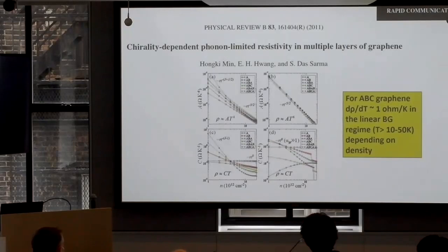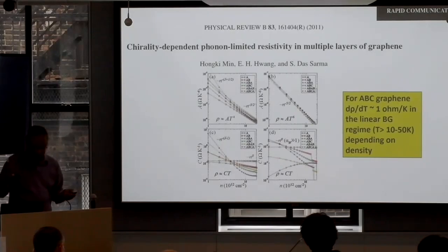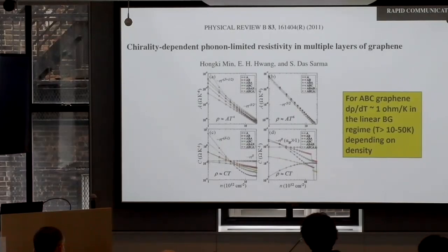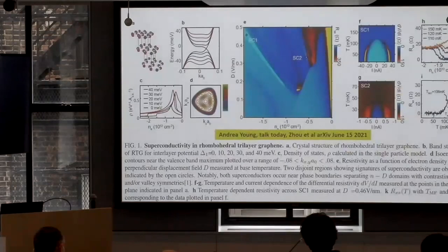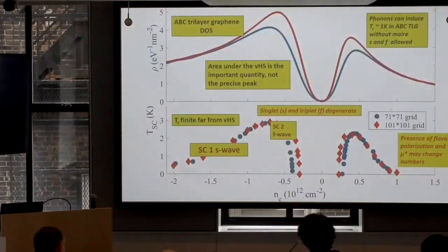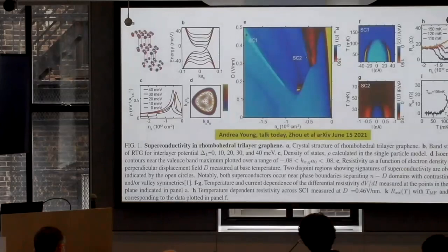A long time ago, we pointed out that for graphene, we originally did monolayer, but you can have multilayer graphene, and you can calculate now, and dρ/dT is 1 ohm per Kelvin, because again it's very small, because the electron-phonon coupling is very weak, and we calculate for all these different materials. So we can now compare, and our prediction is, and this is a very important point, everybody should pay attention. Our prediction is that there should be a linear resistivity in this system, if it's phonons, at some temperature.